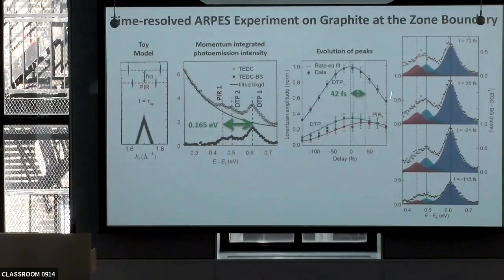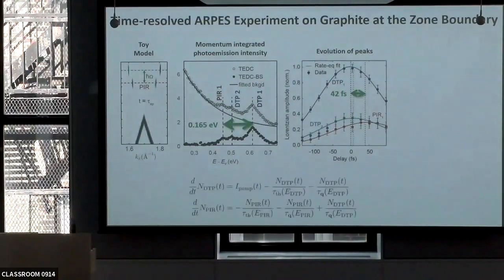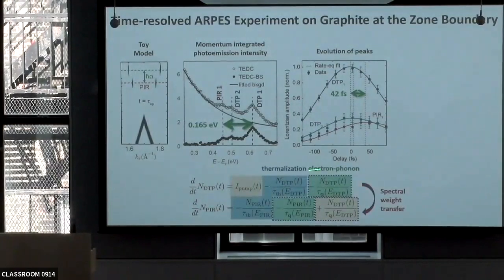So once you have this kind of data, you can interpret that and model that in terms of rate equations. Basically it means I will have an evolution for the intensity of this particular peak, which is driven by the number of electrons which are excited there by the pump, minus the number of electrons which are then lost due to electron-electron relaxation, this tau thermalization, and minus the number of electrons which are lost due to electron-phonon scattering, tau q. So in practice, you can look at these 2 equations, and this is the intensity coming in, and this is the intensity going out. And you have the second equation, which is for the phonon peak, which gains intensity due to a relaxation process, but then loses intensity through the 2 same mechanisms, electron-phonon and electron-electron scattering.